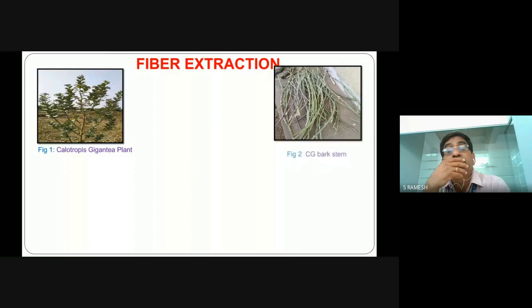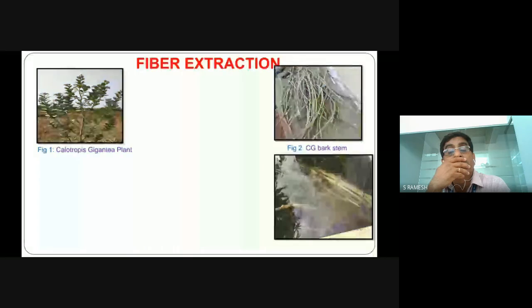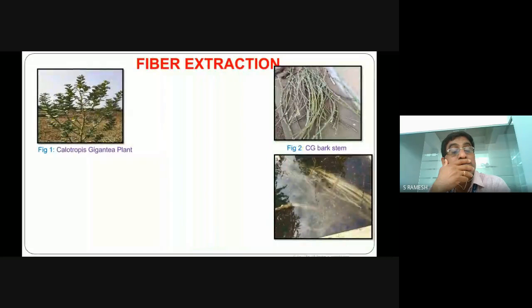And then we will extract the Calotropis gigantea bark stem. We will remove the leaves and the petioles. After that, we will achieve the Calotropis gigantea bark stem. And then we will go for a water retting process, because we have to extract the fiber inside. We will dip it in water for nearly 7 days, and then take it into sunlight for 2 days.